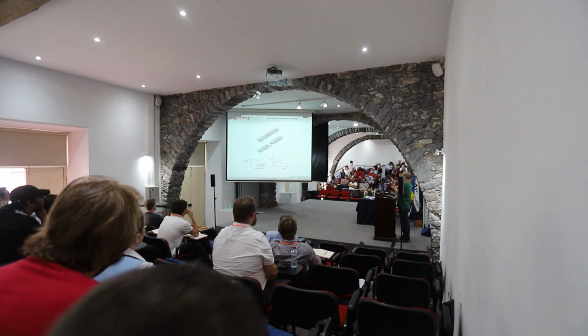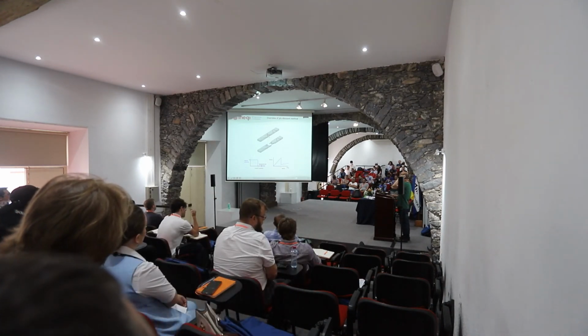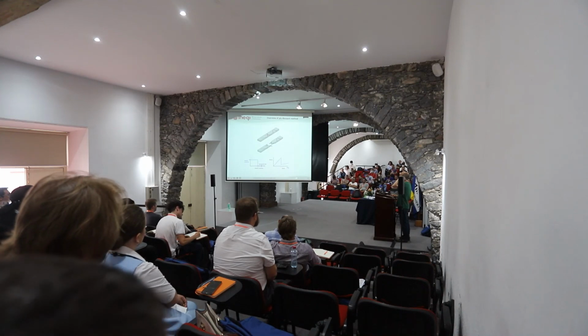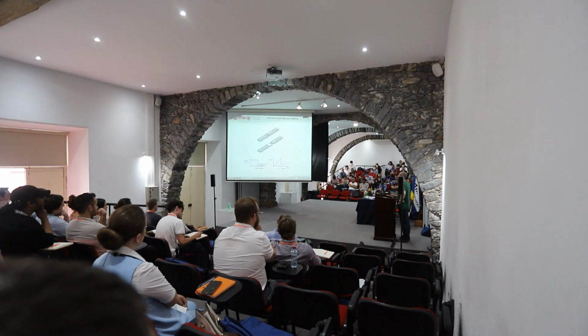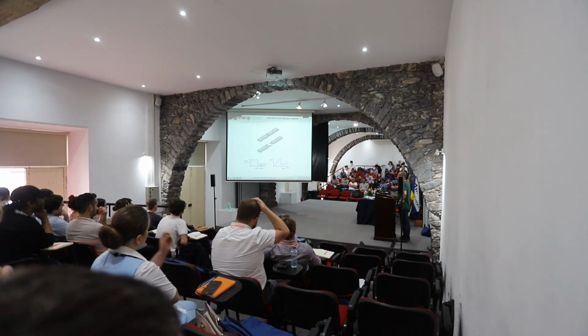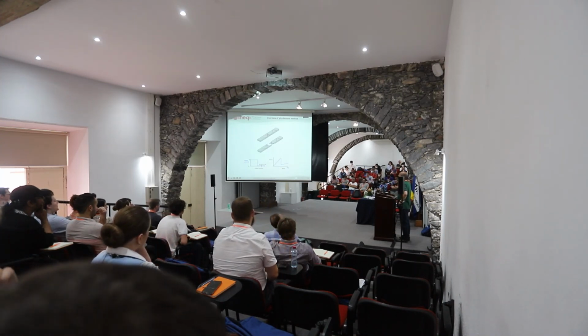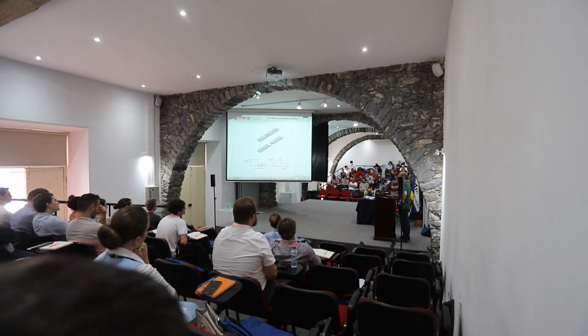still is often seen in some publications, which is the ply discount method. So basically, you try to simulate, like you see in these pictures, these transverse cracks, and then from some strain concentration that you get from one of these cracks, you may have then fiber failure in a different ply. So what people were doing in the, say, early 90s, late 80s was to use a ply discount method, which is not really, I mean, it's a simplified way to capture this, but with some limitations.